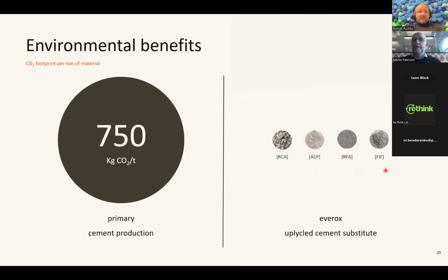In terms of carbon footprint, we have received a third-party LCA, and meanwhile our product is also classified in the European database and also in the Dutch database. So the CO2 footprint of our activated cement paste is only 11 kilograms per ton. If you compare that with primary cement production, of course, depending on the efficiency of the cement plant, 750 is the European average today. So we have a 60 to 80 times less CO2 footprint than primary cement, which I think is very interesting with a local circular material.